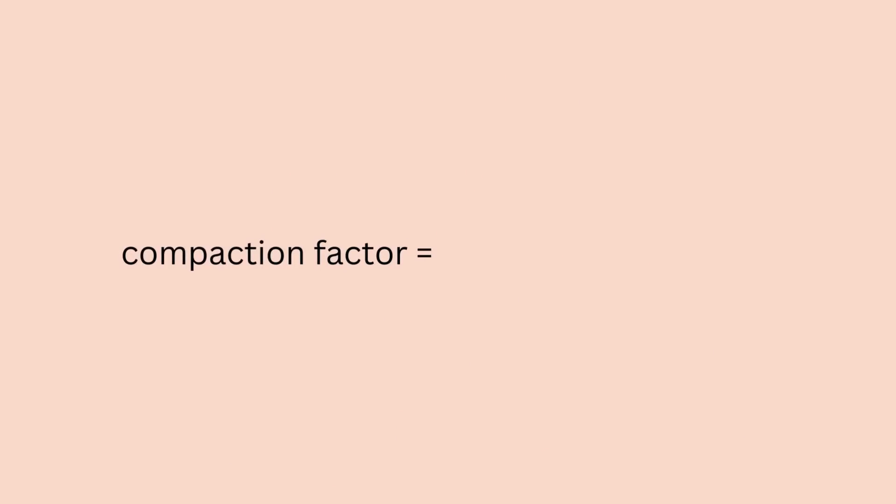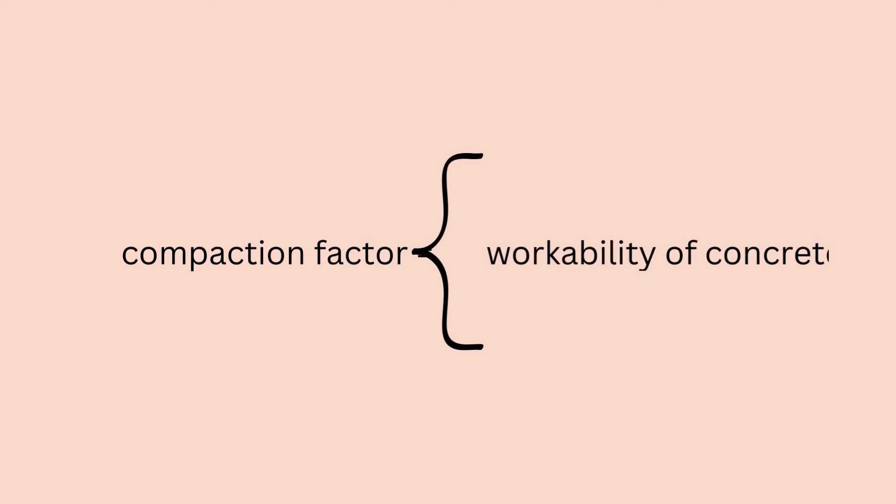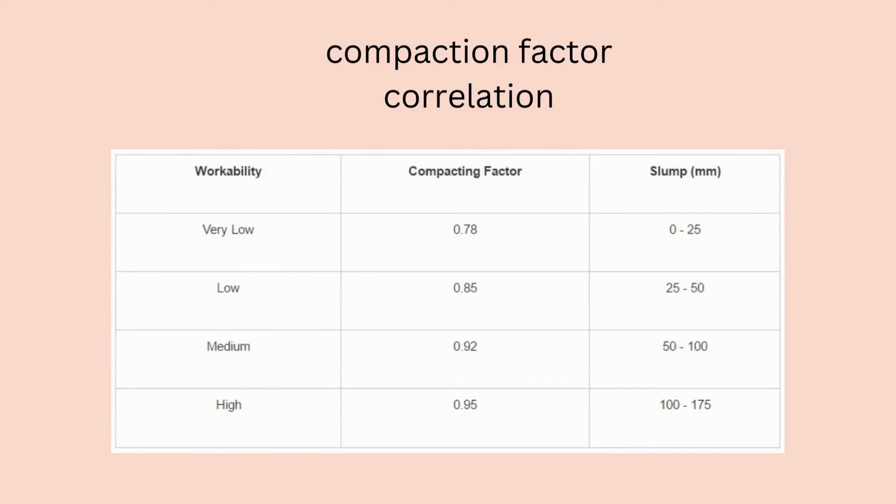Now we can determine the compaction factor as the ratio between the weight of partially compacted concrete with the weight of fully compacted concrete. We can correlate the value of compaction factor with the degree of workability using the table. The more the value of this factor the more will be workability of concrete.